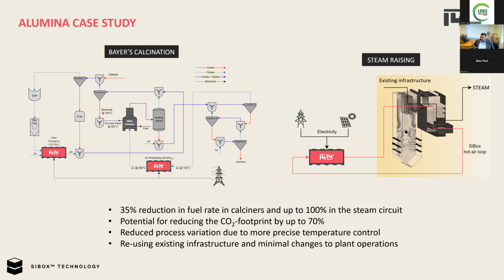One is for the Bayer calcination process, where you need to provide heat to the main furnace, or maintain the furnace temperature, at about 950 to 1,000 degrees Celsius. The opportunity for SiBox to integrate in such a process comes from air preheating, and also from preheating some of their feedstock, which is gibbsite. When it goes into the main furnace, it is already hot, instead of what they use currently. This has multiple advantages, not just in reducing the fuel rate in the calciners, but also in increasing the productivity of the plant as such.